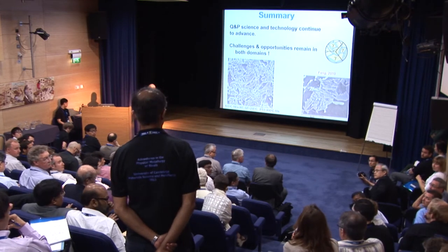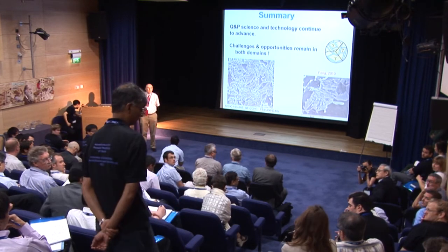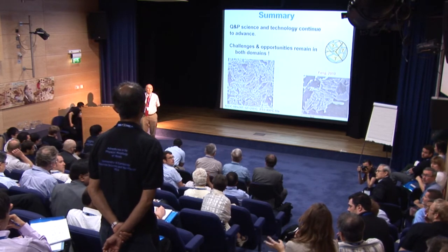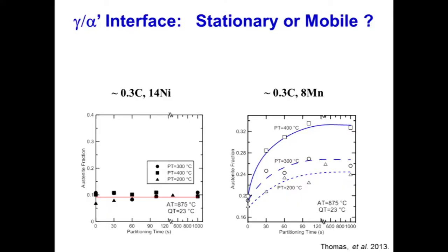Okay, thank you for your talk. I have a question regarding the results from Thomas on the high nickel and high manganese steels, in which he observes an increase in the fraction of austenite during the partitioning step. I know that at those temperatures the diffusion of manganese is extremely small, but I also saw some articles from other researchers who think that the diffusion of manganese is underestimated at low temperatures. So do you think this increase in the austenite fraction can be due to some manganese partitioning, actually?